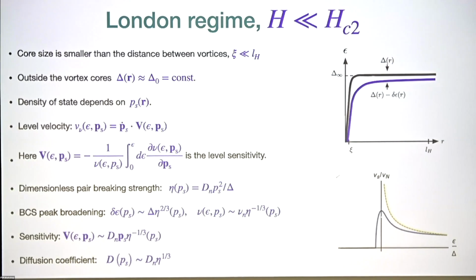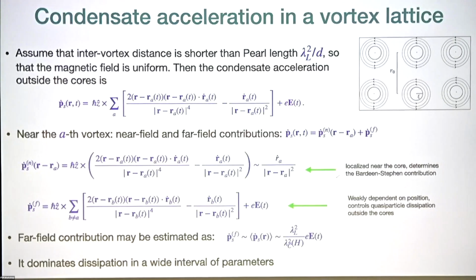And everything we need, like the width of the broadening peak delta epsilon, are powers of this pair breaking parameter. Also, the height of the density of states at the peak also scales with this pair breaking parameter, and so does the sensitivity. And the only new input we need in comparison to uniform systems is the diffusion coefficient for quasi-particles in this broadening region. It's not equal to the normal state diffusion coefficient, but is also affected by pair breaking. And then with these inputs, we can try to understand what's going on in superconductors.